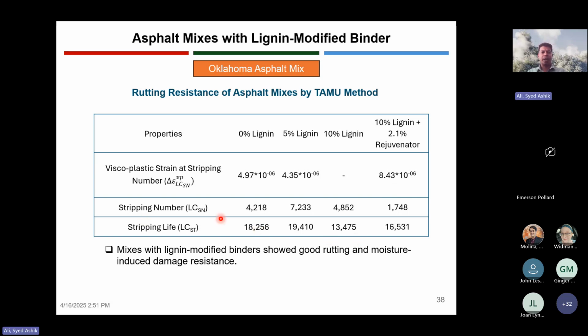But stripping number wise, we have found it's pretty good. A higher stripping number shows less susceptibility to moisture. So we have seen pretty good results with the addition of lignin. We have seen an increase in stripping number, and the stripping life also indicates good moisture resistance of the lignin modified asphalt binder.